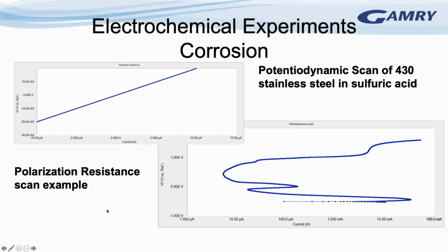So for corrosion experiments, here are two examples. On the top left, we have an example of a polarization resistance scan, where the voltage is scanned from 10 or 20 millivolts below the open circuit potential to 10 or 20 millivolts positive of the open circuit potential. And the open circuit potential is the resting potential of the material that you're studying in the solution of interest.